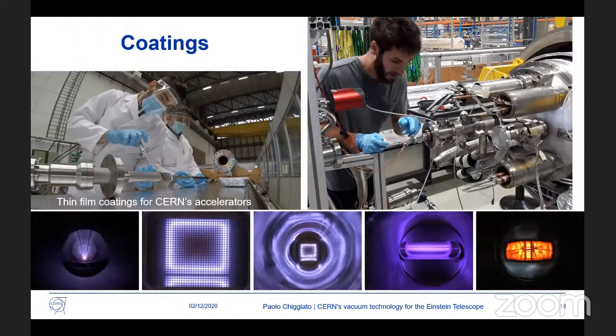So another pole of expertise in the group is coatings, thin film coatings. And our experience focuses essentially on one main activity, which is coating in situ, so inside the accelerators. As you see here on your right, we are preparing for coating inside a cryomagnet. This is a prototype of an amorphous carbon film to reduce multipacting phenomena. And the magnet has a 5 centimeter diameter bore and is 16 meters long. Another important activity is coating in big vacuum chambers with a high aspect ratio, with a length of a maximum of 8 meters, because this was required by accelerators, but in theory there is no limitation for that.